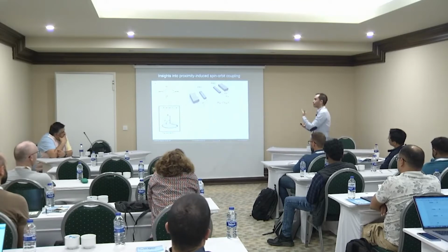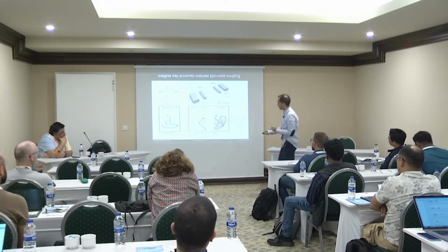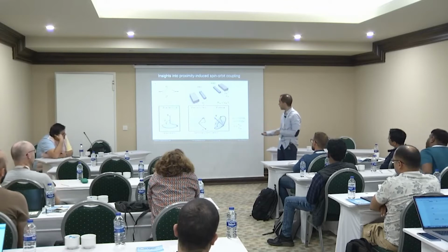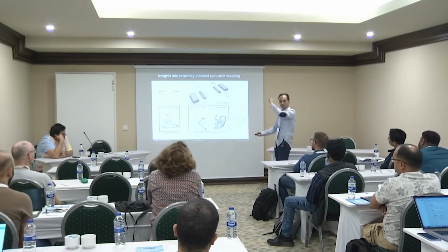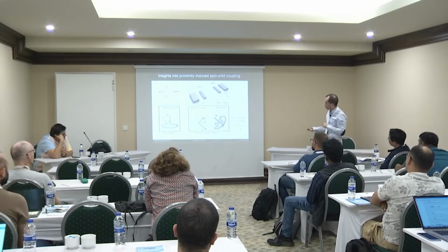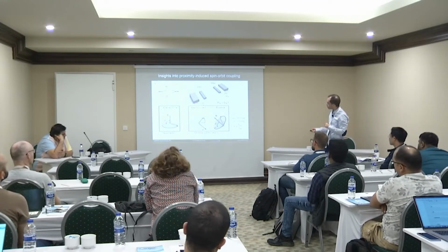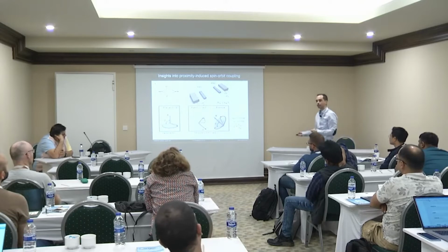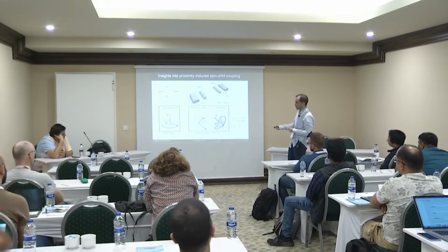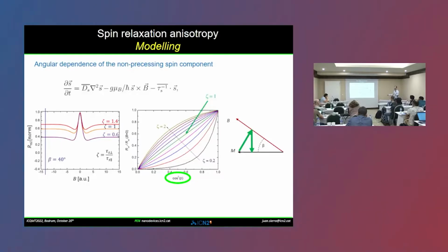So we have to develop something. There is an evident configuration: you can apply the magnetic field along the spin channel direction. In this case, you have spins that are precessing out of plane, but this has some technical disadvantages. What we developed in the group a few years back is an oblique technique in which we apply the magnetic field at specific angles with respect to the easy axis of the ferromagnet. If the anisotropy is larger than 1, you have these lines that are above, or if it's smaller than 1, the representation will be below this line.